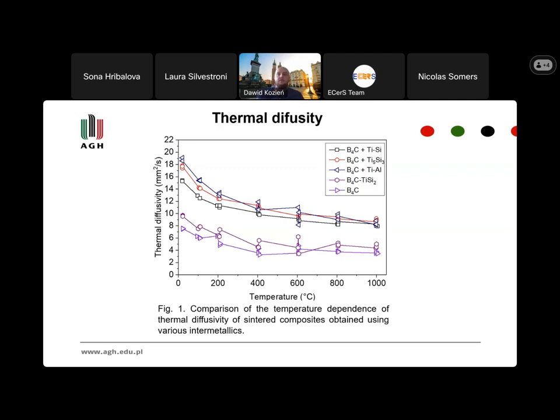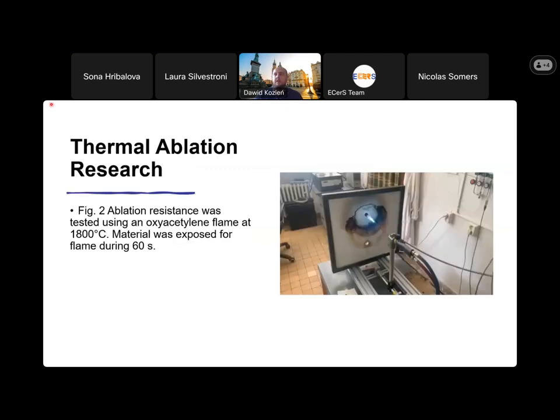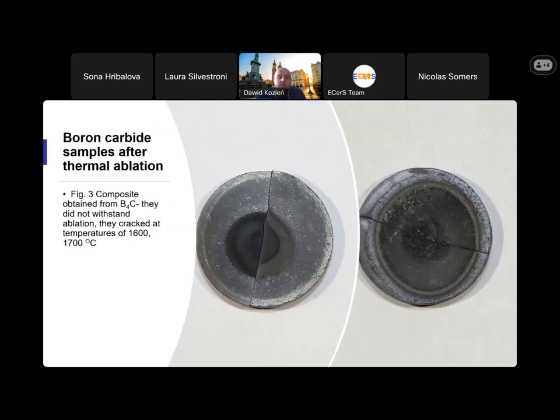So we checked the thermal diffusivity of this material, and you have the comparison of the temperature dependence of the thermal diffusivity of sintered composites using various intermetallics, compared to boron carbide. I don't know if you see the movie. Maybe now it's not working, but after that I can show that we checked the ablation resistance test using the oxyacetylene flame at 1800 Celsius degrees, and the material was exposed to the flame for 60 seconds. So we prepared the composite and we want to see how they look after this method. And to compare, you can see how typical boron carbide looks after something like that, that it cracks at a temperature of about 1600 to 1700 Celsius degrees, how it is cracking.